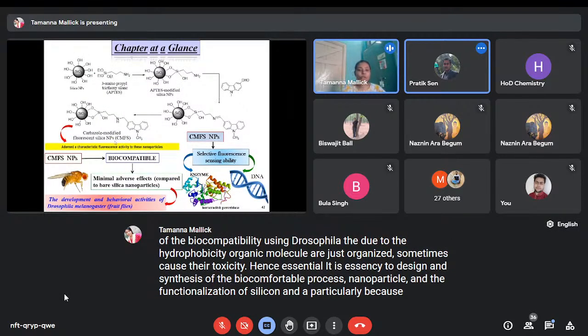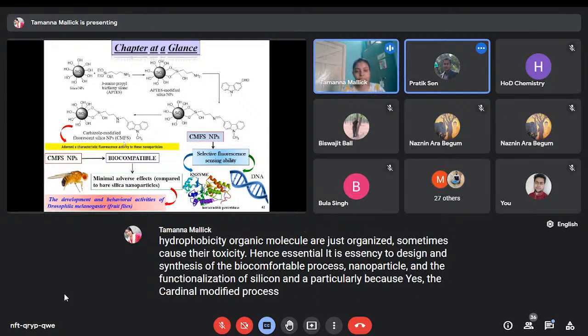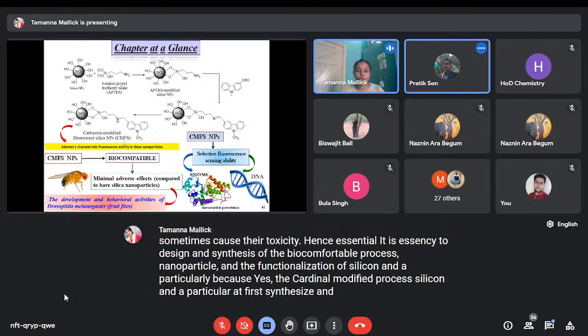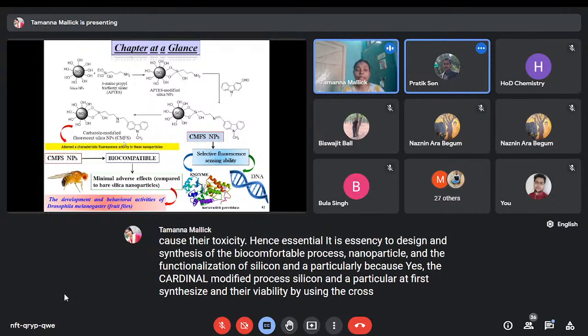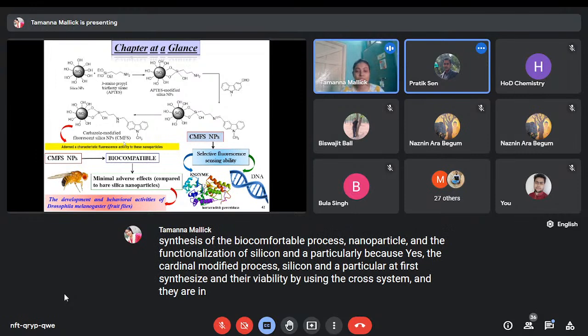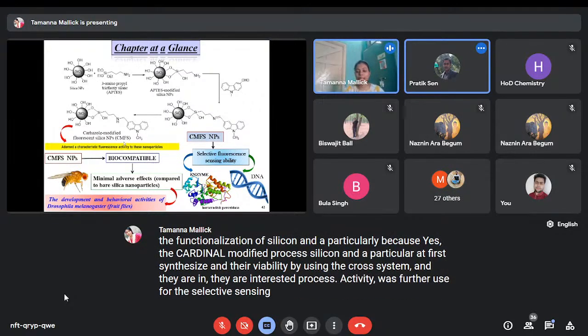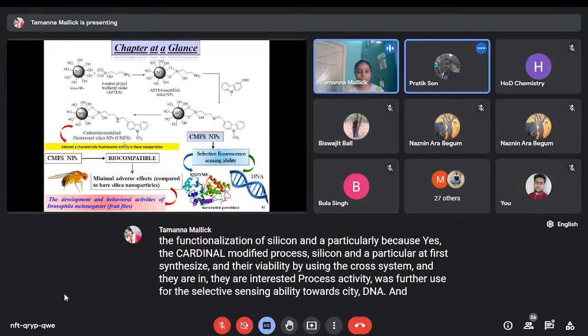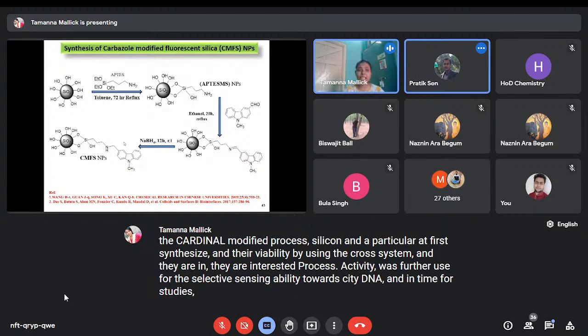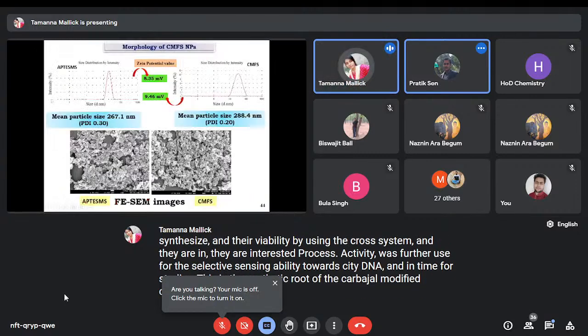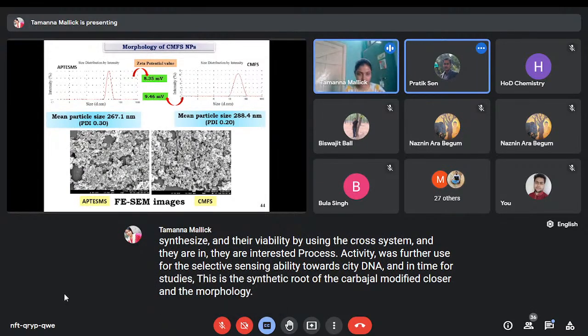Here, the carbazole modified fluorescent silica nanoparticle was first synthesized, and its bioavailability was checked by using Drosophila melanogaster as a model system, and its intrinsic fluorescence activity was further used for the selective sensing ability towards ctDNA and the enzyme horseradish peroxidase. This is the synthetic route of the carbazole modified fluorescent silica nanoparticle, and the morphology was checked by using the DLS and the FESEM image.